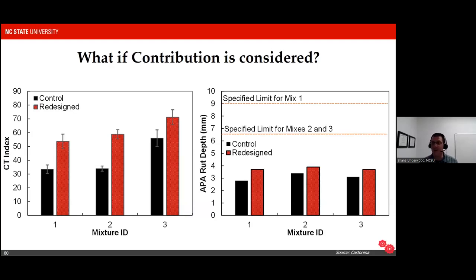But what can't be done is to blindly add in recycled materials and hope that they perform better. Because as we showed in the North Carolina case, when you do that, you run the risk of truly negatively impacting performance. And if that happens, then all of the benefit that you see in using recycling materials may be lost because of increased maintenance costs, increased disruptions to traffic because those repairs are being made, and other negative consequences. So what I want you to take away from this is we just need to be very careful using recycled materials, not to run into using them for the goodness of their resource consciousness and now end up losing performance and creating actually a worse situation that has more negative impact on the environment and on our economic well-being.